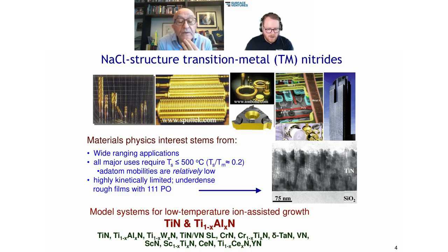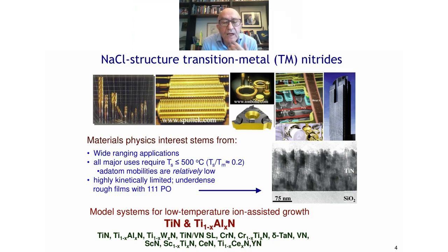So even at 500 degrees Celsius, which is only 0.2 of the melting point, we get very poor films, as illustrated in this cross-sectional TEM. Porous, rough films. And that's why they have been used, as I said, as model systems for ion-assisted growth. I will use titanium nitride to demonstrate how metal ions affect the growth. This is generally typical for many other nitrides that I have listed below, which have the cubic structure. Next slide, please.